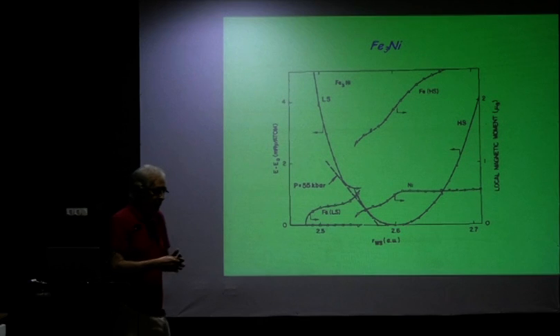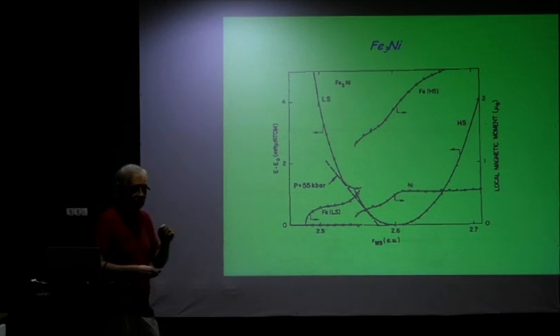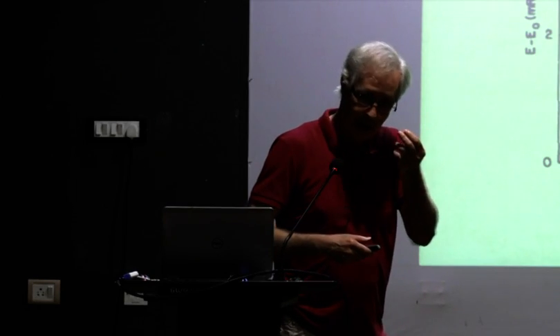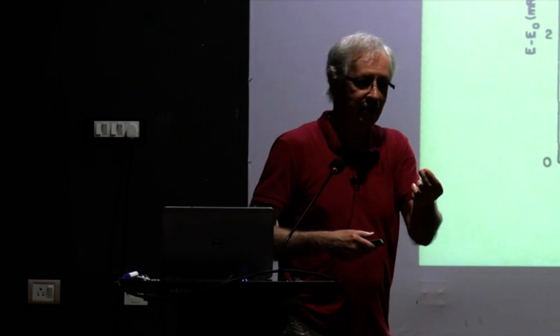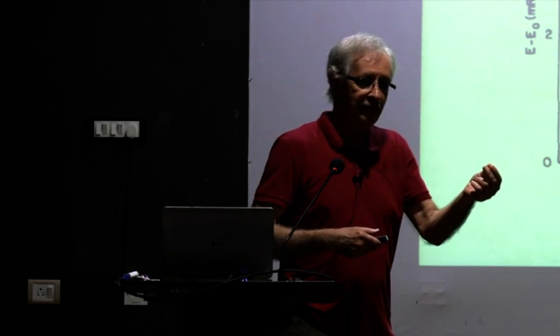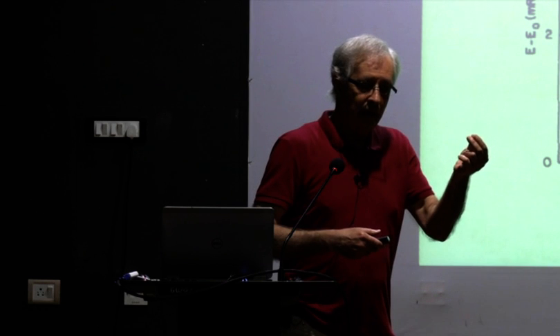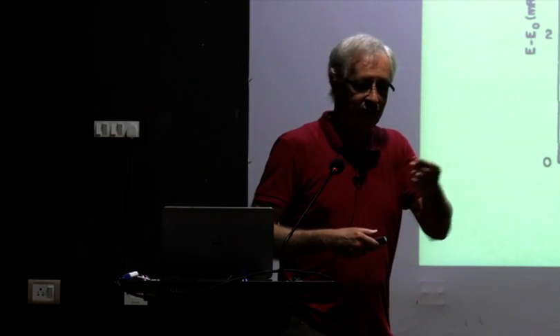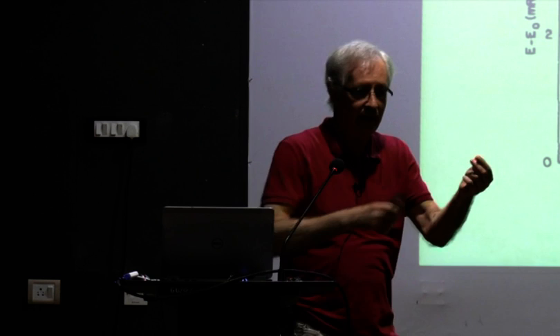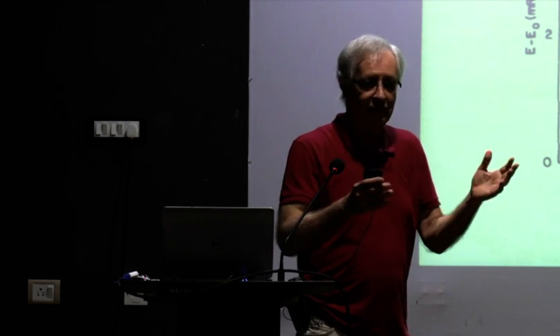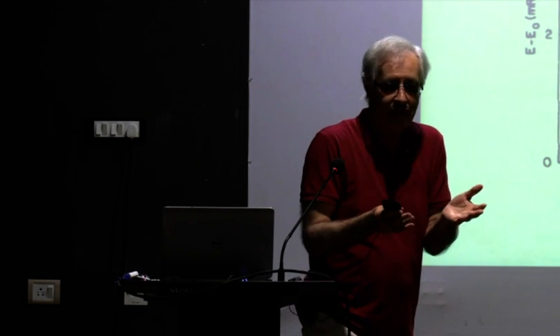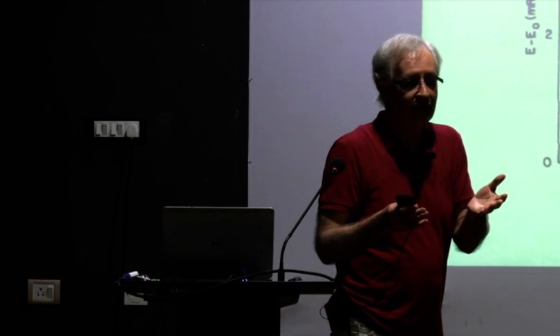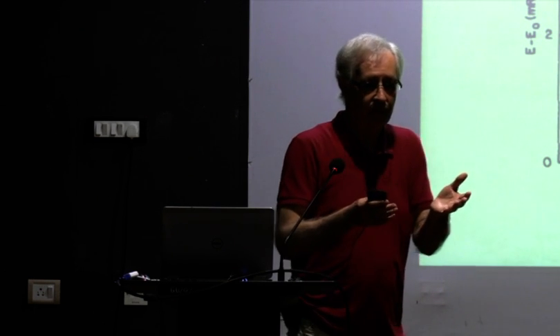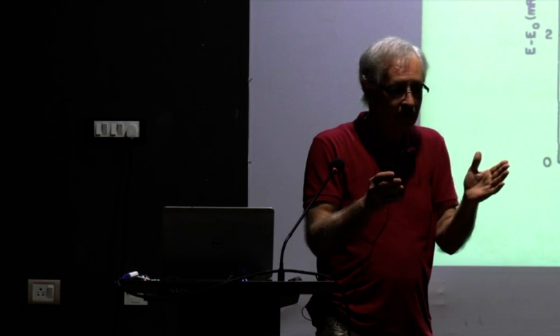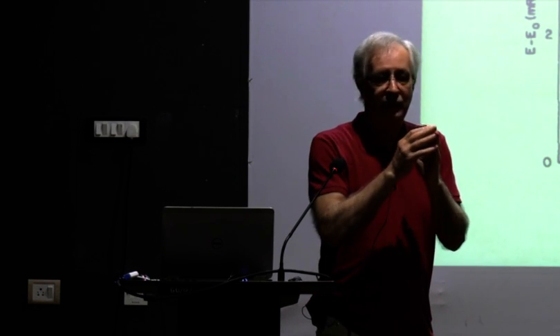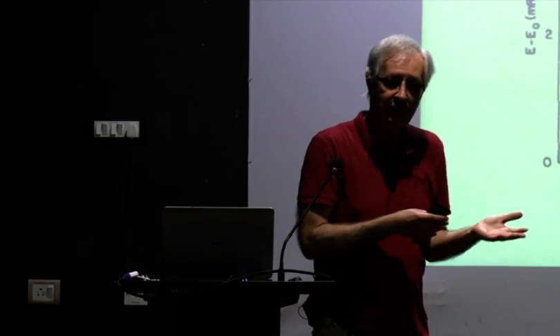Okay? So the magnetism is taking you from a high magnetic moment, high volume state, to a low magnetic moment, low volume state at a higher temperature. And this is counteracting the regular thermal expansion. And this is precisely what the INVAR effect is experimentally. If this compensates fully, then your thermal expansion is zero. And that is exactly what we see.